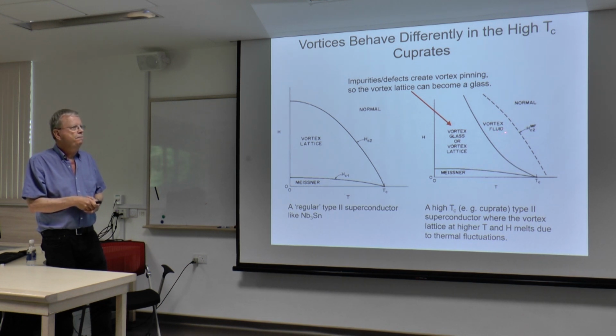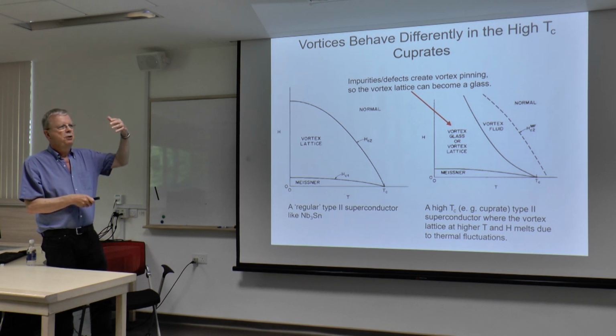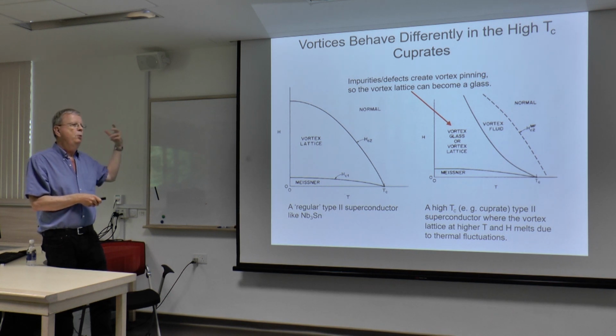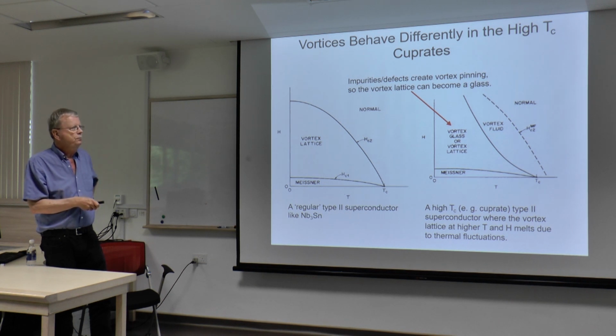So the High Field Magnet Laboratory in Tallahassee put into operation for users, which is very courageous because users are rough on equipment, I believe it's a 33 Tesla high TC cuprate magnet in this calendar year. So it's available for user use. So it is possible to get a high field magnet above 23 and a half that you get from the old low TC A15 structure in niobium 3 tin, which again we'll talk about in lecture 2.